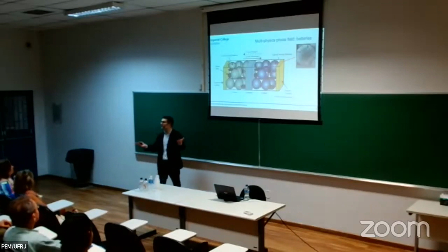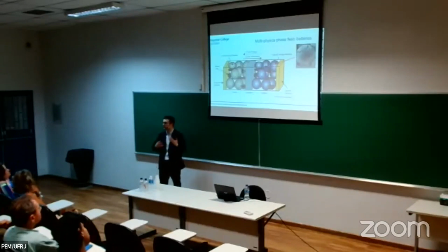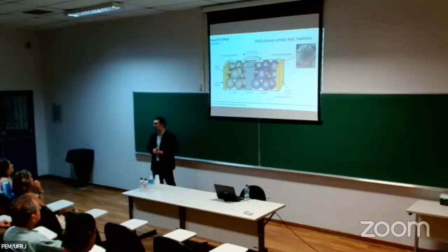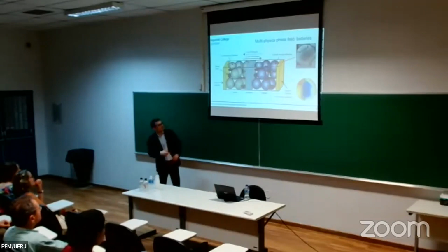So we try to use those models that I presented before, these multi-physics based fracture models, to predict under what conditions we will see those cracks and to try to map safe regimes of operation of those lithium-ion batteries. And you can see here, the idea is quite simple and quite similar to the previous model. The equations are almost the same. You can see that we have again a three-field problem. In this case, we're modeling lithium diffusion instead of hydrogen.